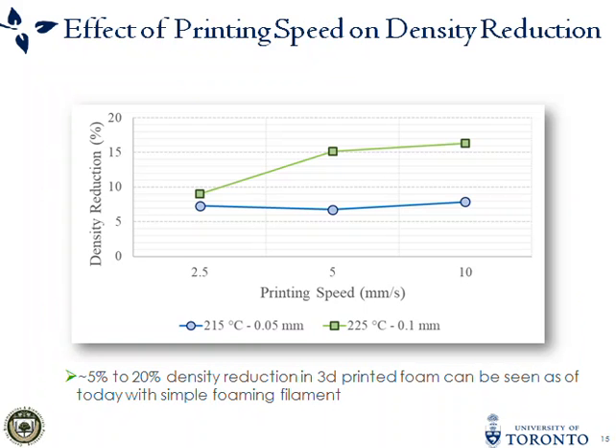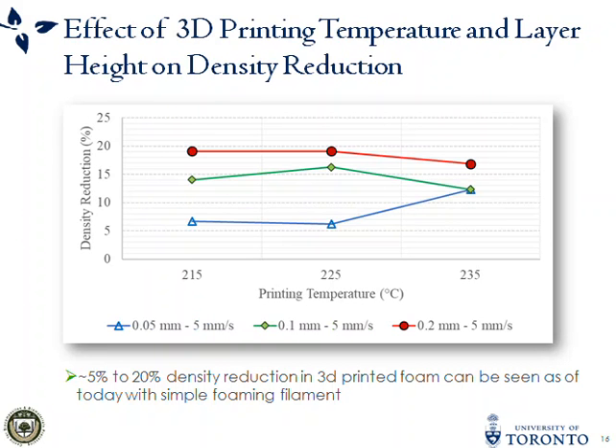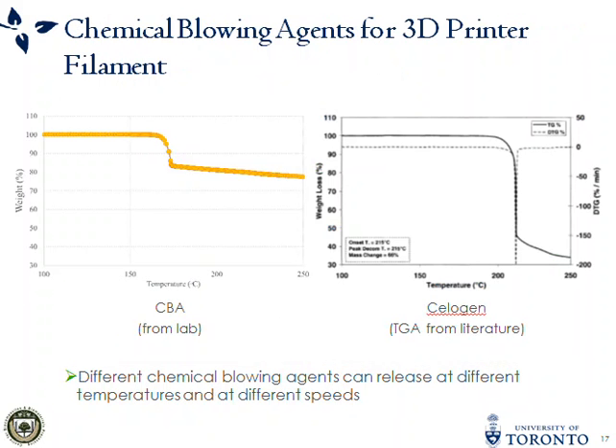So the chemical blowing agent that's released during this process is affected by a lot of different 3D printer settings. One is printing speed. There are many variables that you could change in the printer settings, but there are a few very important ones. Temperature and layer height are very important. The temperature obviously releases blowing agent, and the layer height affects the compression between the layers and the nozzle while it's being extruded. We can also use different blowing agents.